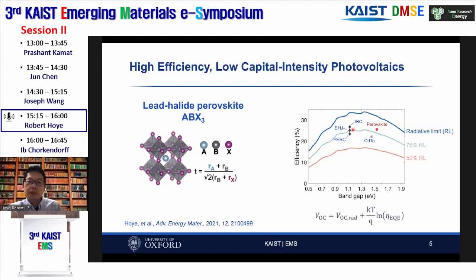And one of the key requirements to reach this high level of performance is to have a very low rate of non-radiative recombination. So for example, here's an equation that relates the open circuit voltage, the highest voltage you can get from a solar cell, to your theoretical limit. You can see that the relation depends on how high the external quantum efficiency is, which also depends on the photoluminescence quantum yield. So for the VOC to approach the radiative limit, we need to have very high EQEs approaching 100%.